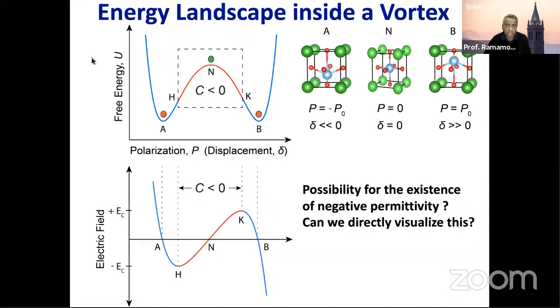Now, here's the interesting piece in the double well structure. If I looked at the second derivative of the free energy, which is really the permittivity of the material, right here, that derivative was negative. And therefore, the material is not stable in this state. Instead, it'll roll down to this point and this point, where the curvature of the free energy is positive and the material is stable. Okay, and so you could also explain it in terms of the electric field. So what you can say is that typically the negative permittivity state is not stable in the system. In just a couple of minutes, I'm going to show you, oh, by the way, that may not be true. All that this is saying is that for the entire material, negative permittivity is not stable, because that will automatically lead to this thing rolling down the hill to go to this point, where it is positive permittivity.